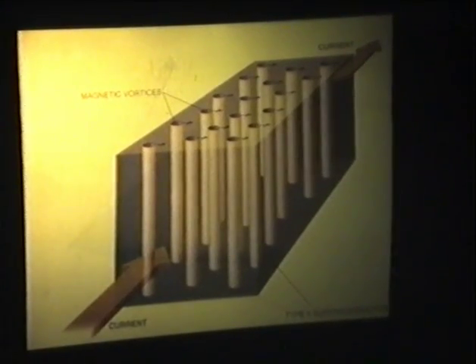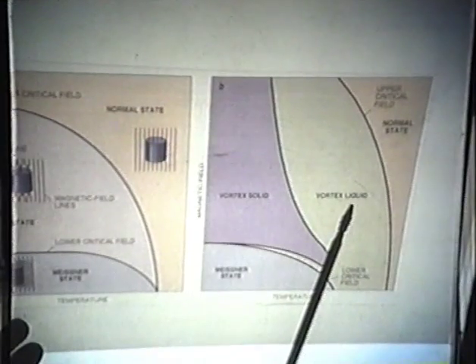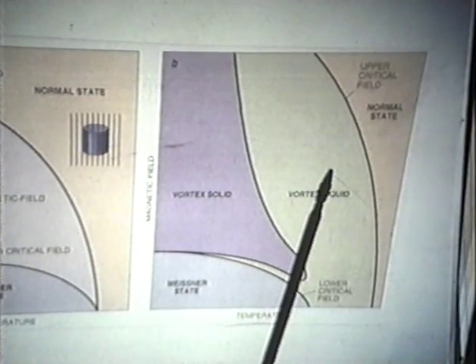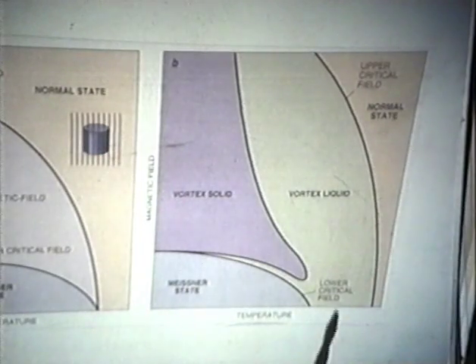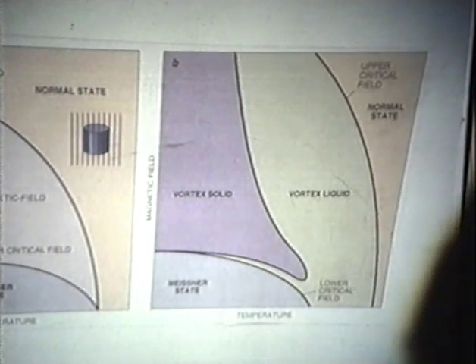And here the superconductor kind of sacrifices itself even more strongly than it normally does in the vortex solid, as a consequence of their remarkably high critical temperatures. And the vortices, instead of being locked in place, actually wander about under the influence of currents and what have you. So all the vortices are jumbling around. And even though it's still a superconductor, the jumbling around of the vortices in the vortex liquid dissipates energy. And so you can find you've got a superconductor in this state at a particular temperature and a particular field, which has got a resistance greater than copper at the same temperature, even though it's still superconducting and it's still Cooper pairs carrying the currents. So that is a real problem because that's the high temperature region where you might want to operate these things in liquid nitrogen.